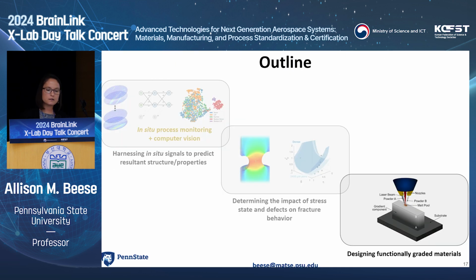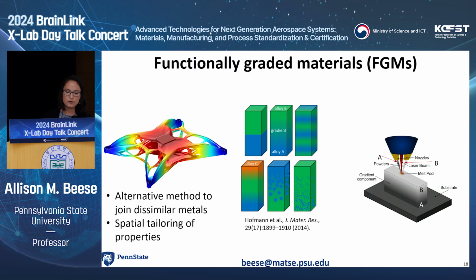All right, in the last few minutes, I'll talk about functionally graded materials, where in this case, we want to think about putting different properties at different locations within a complex component by changing the chemistry. So this is an example schematic to show, okay, if these colors represented things like thermal conductivity or stiffness or magnetic permeability, we could get different properties at different locations by putting different materials in different locations. So we can use this to join dissimilar metals or tailor properties, and for this we use directed energy deposition and deposit different materials from different hoppers as a function of position.